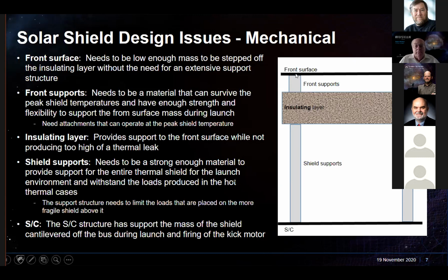So again, you need to have low mass on the front surface, and you'll be able to spread that mass into the insulating layer that's necessary at the carbon-carbon front surface that's helping move the loads into the sandwich structure. Far down, you have what I will call a regular structure. So this is a titanium truss or something like that that's holding the weight of the whole system off the spacecraft. It's supporting the launch loads. It's supporting the thermal loads that are happening during orbit.